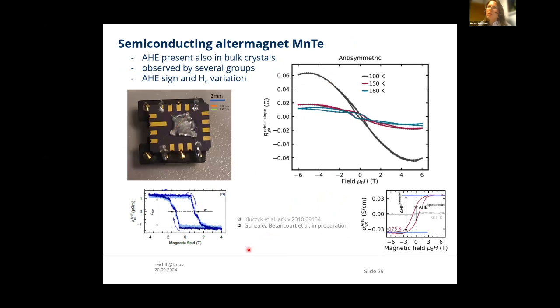So here I just put one slide to note that manganese telluride is a beautiful system, but there are also open questions. One of them is, for example, that we now also look at bulk crystals, not only films, as do some other groups. I know, for example, this group, but there is also a group in the US which has beautiful data on bulk manganese telluride crystals. And indeed, also in the bulk crystals, we observe a spontaneous anomalous Hall effect.